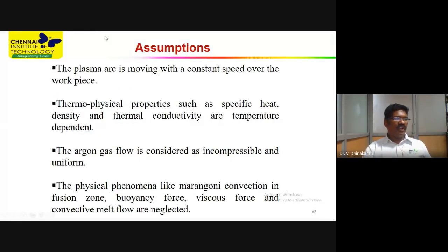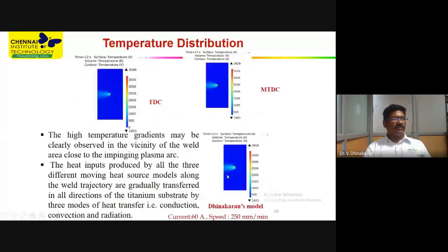So assumptions have to be considered, and I considered temperature-dependent thermal properties, and the argon gas flow is considered as incompressible and uniform flow. The temperature distribution has been calculated by using the already available heat source models: the three-dimensional conical heat source model, the modified three-dimensional heat source model, and Dhinakaran's model. These three heat source equations have been utilized to find the temperature distribution, and it is found that Dhinakaran's model predicts the temperature distribution more correctly than the other two models.